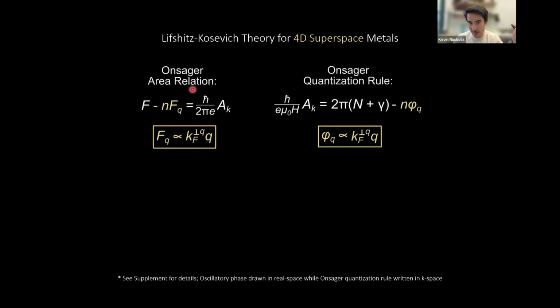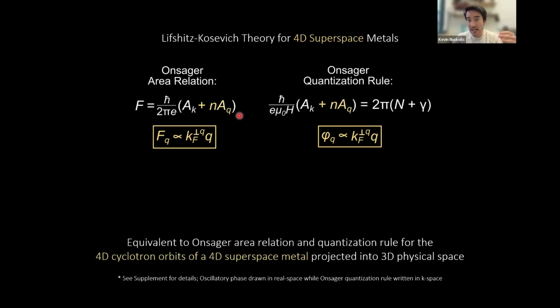And so bringing back that Onsager area relation and quantization rule, I actually will show you that this anomalous frequency, anomalous phase shift, they're not only proportional to Q, but they're proportional to this Q vector times the Fermi wave vector that is perpendicular to the Q. So if you look at this quantity very carefully, you'll recognize that actually this has the units of area in momentum space. Momentum, so it's a momentum squared. And so what this entices us to do is to take this form and to fold it back into the area in each of these Onsager relations in order to recover an Onsager area and quantization rule.